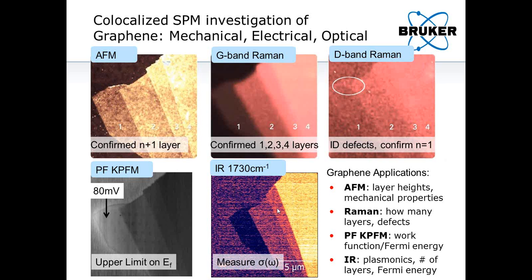And then of course we have our first scattering SNOM results on this sample, which I show in this last image here, and they were obtained in the universal conductivity regime. And images such as these allow us to get information about graphene's optical conductivity.